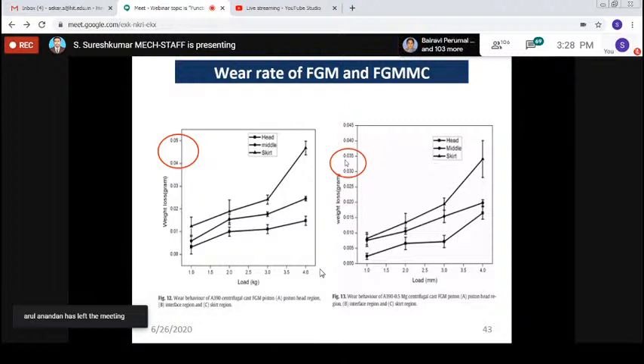The wear rate reported for both materials, the aluminum alloy and the aluminum alloy based composites produced by vertical casting. As I told you, the head side has more reinforcement and the bottom side has less. So you can compare the wear resistance, I mean the weight loss after the wear test; the weight loss occurred on the material is comparatively less. My point is that it indirectly indicates that the wear resistance of the head section is higher than the middle section and the skirt or bottom side.